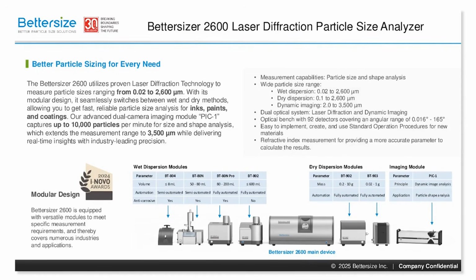Now, let's talk about the Bettersize 2600 laser diffraction particle size analyzer itself. Its tagline, "Better particle sizing for every need," really sums it up. This award-winning instrument, recognized with the 2024 iNovo Award, offers unparalleled measurement capabilities with its modular design, from paint suspensions to pigment dry powders. With its unique optical design, the Bettersize 2600 boasts an exceptionally wide particle size range, handling everything from 0.02 to 2,600 microns with wet dispersion and 0.1 to 2,600 microns with dry dispersion.